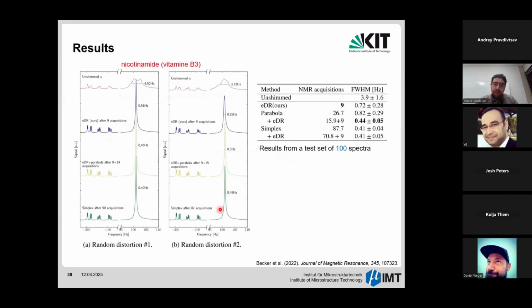Okay. And we also tested this model with a sample that was not used for the training. We always used water for training. Here is the spectrum of vitamin B3. And as you see, here's the starting spectrum. That's the unshimmed spectrum with a line width of 4.5 hertz. Then when we apply our enhanced deep regression model that requires 9 acquisitions, 7 random steps and 2 predictive steps, we already get to 0.51 hertz.